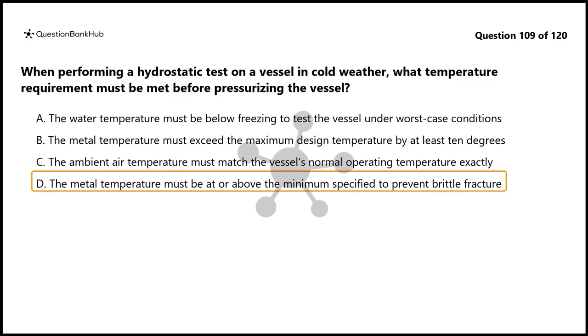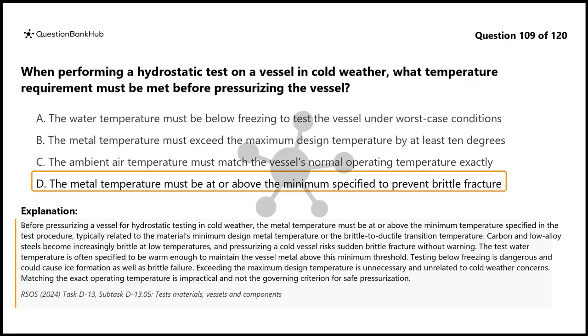The correct answer is D. Before pressurizing a vessel for hydrostatic testing in cold weather, the metal temperature must be at or above the minimum temperature specified in the test procedure, typically related to the material's minimum design metal temperature or the brittle to ductile transition temperature. Carbon and low-alloy steels become increasingly brittle at low temperatures, and pressurizing a cold vessel risks sudden brittle fracture without warning.